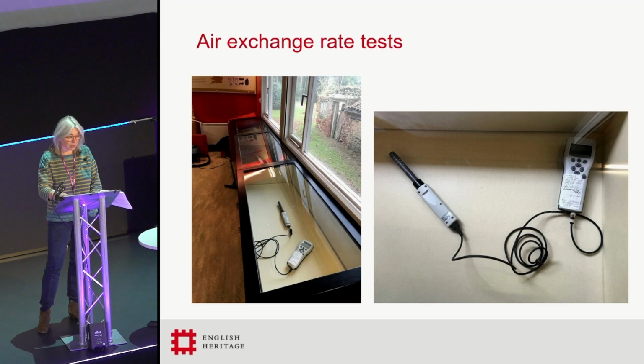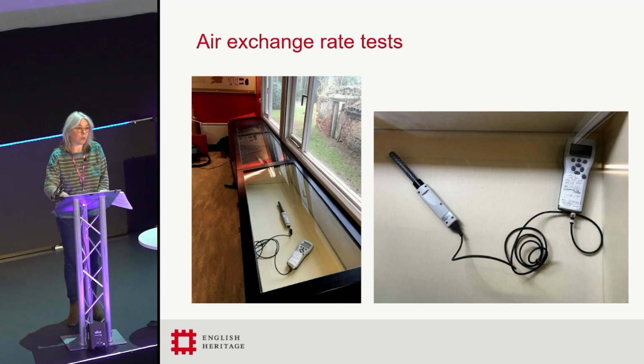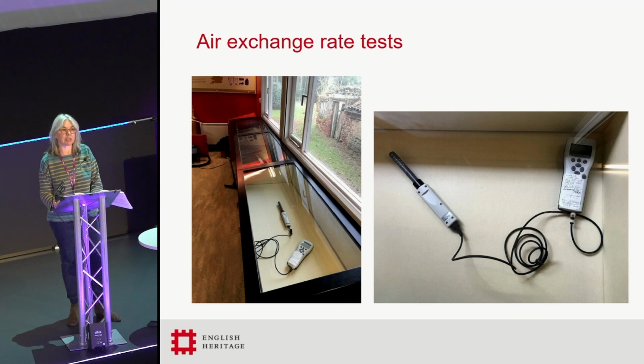Desiccant material will last longer, but will increase risk of any pollutant buildup from sources inside the case. High air exchange rate equals poor air tightness, can make RH control very difficult to maintain long term and increases the influx of external pollutants and dust. So air exchange rate can be measured in several ways, but one of the simplest ways is using a tracer gas, such as carbon dioxide, injected into the case. The carbon dioxide concentration is monitored using a logger inside the case to measure the time it takes to disperse.